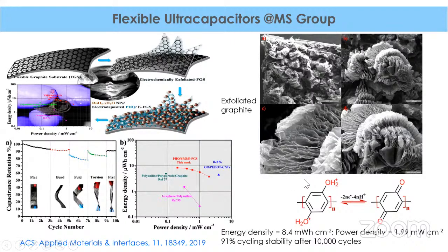He electropolymerized this polyhydroquinone. So this has been used again as a redox entity, and it also improves the surface wettability of this graphene. So this entire assembly, one electrode, has been made with these graphene sheets coated with ruthenium oxide and polymer, and then another electrode, and then a PVA H2SO4 polymer gel electrolyte has been sandwiched in